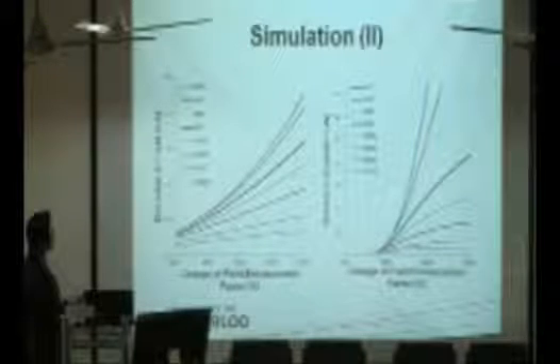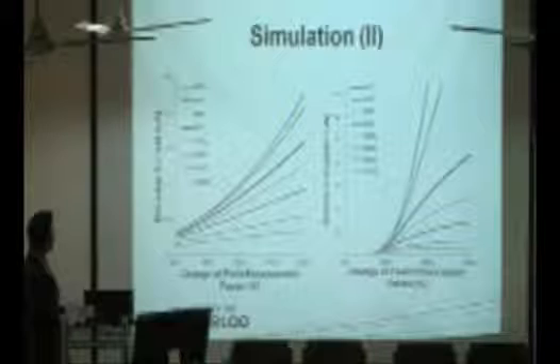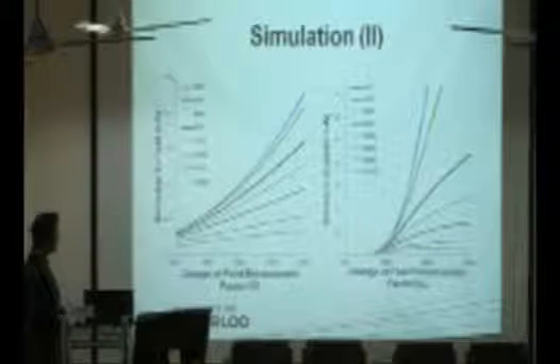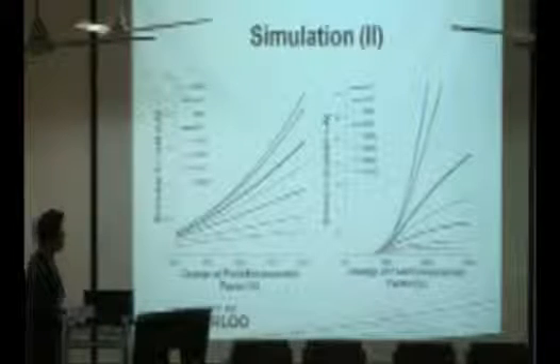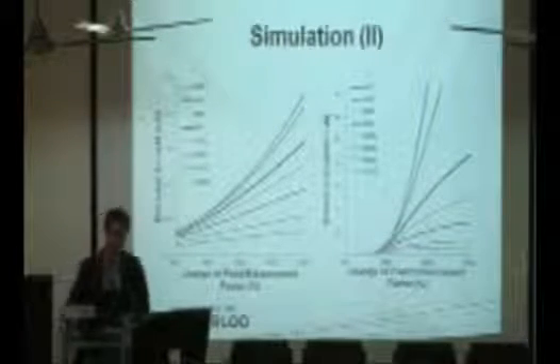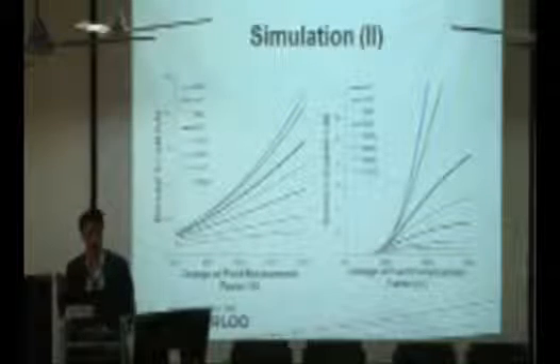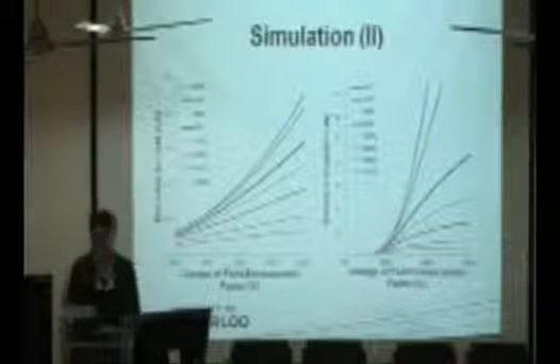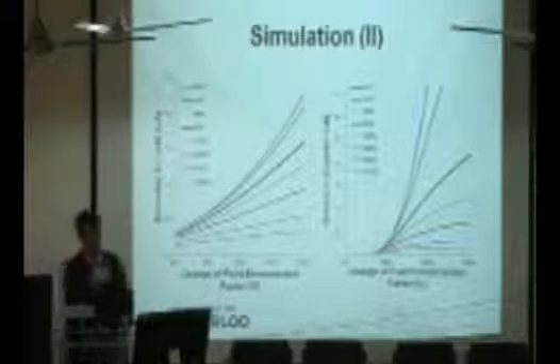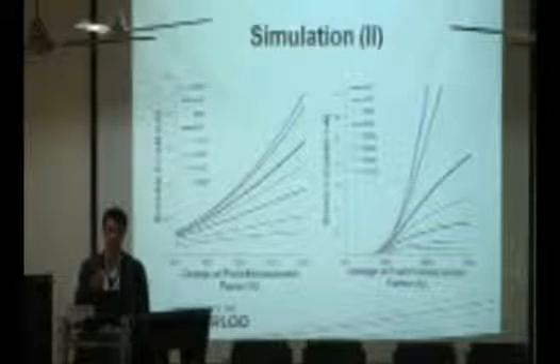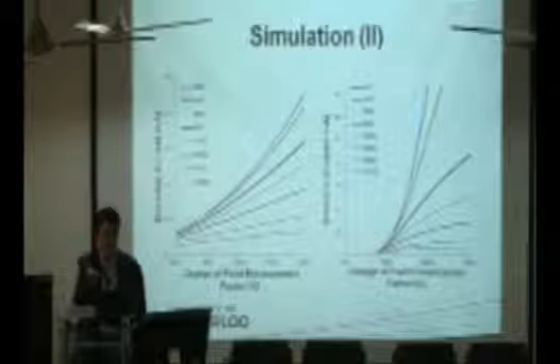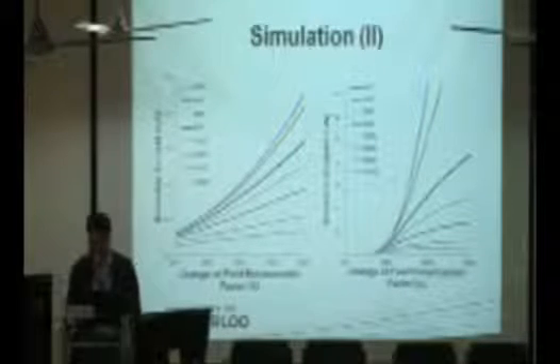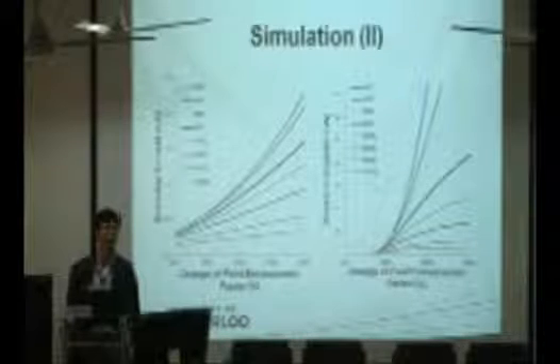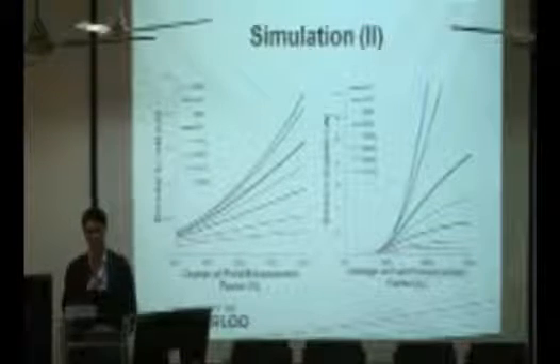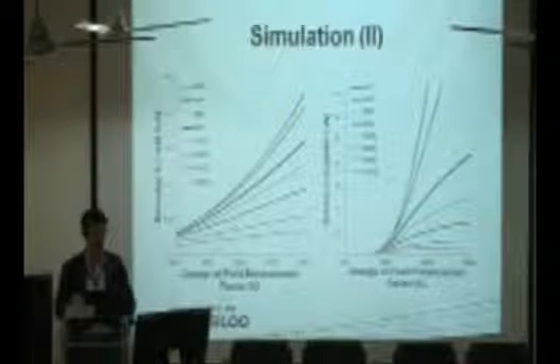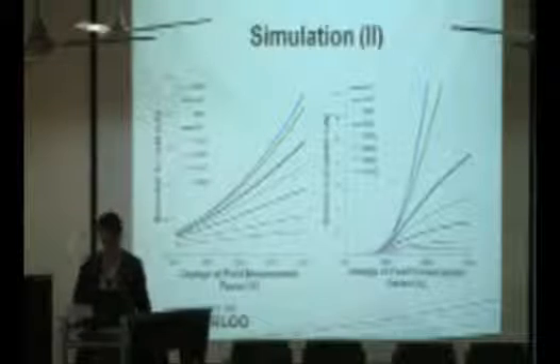from 0 ohms to 100 ohms. You could see that the emission current is effectively suppressed as we increase the resistance of the ballast resistor. Now, one could obviously say you have solved the non-uniformity problem, but now you are extracting less current. But we can obviously increase the electric field to increase the current level, and at the same time maintain the uniformity of the current extraction. So at this point, at least from a theoretical point of view, we are convinced that by incorporating a resistor underneath an array of carbon nanotubes could potentially solve our problem.